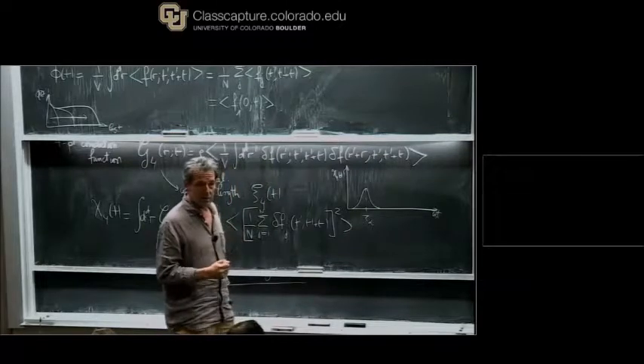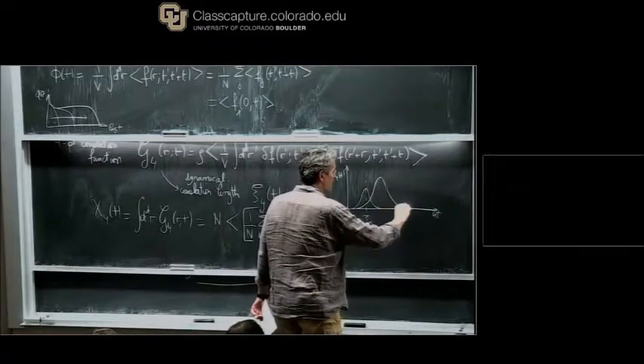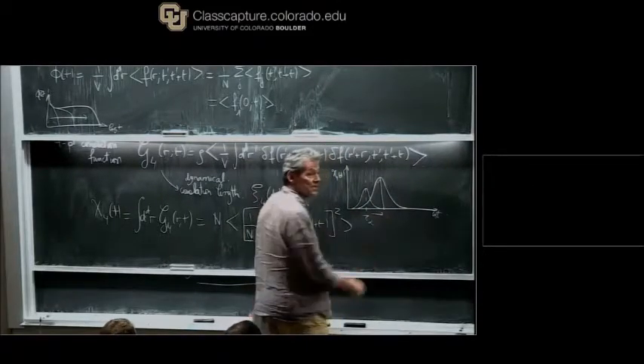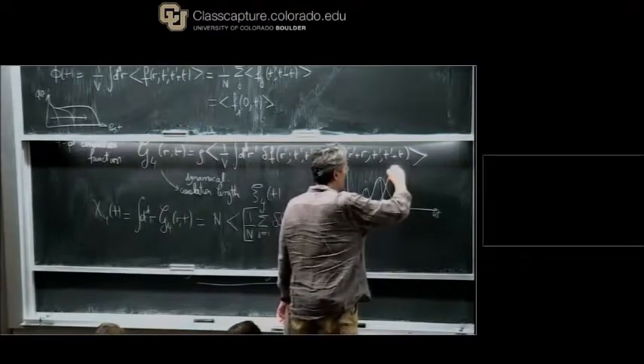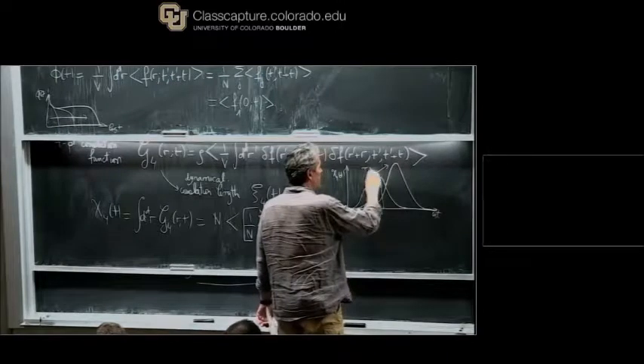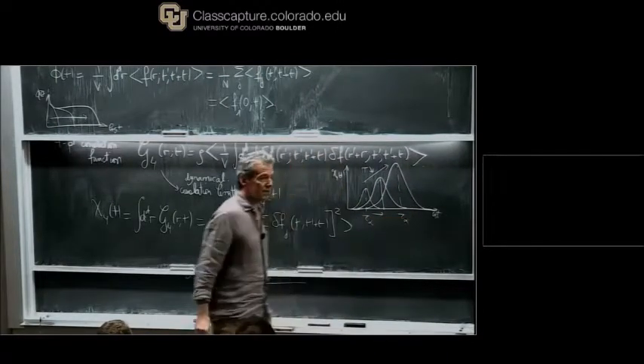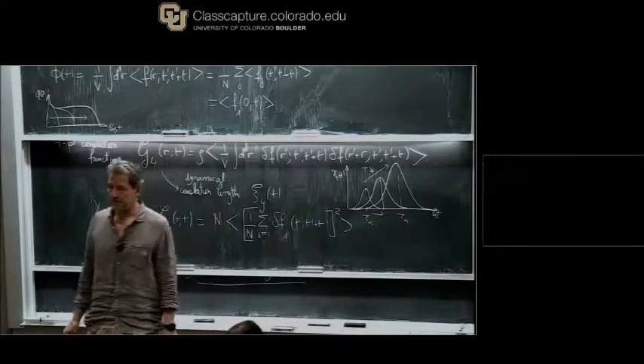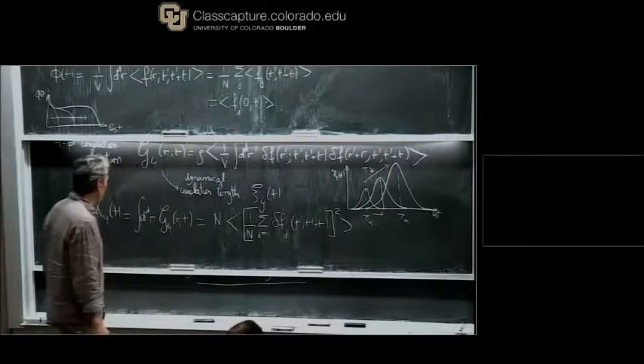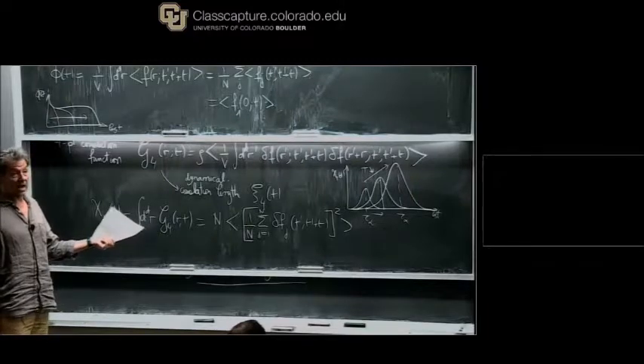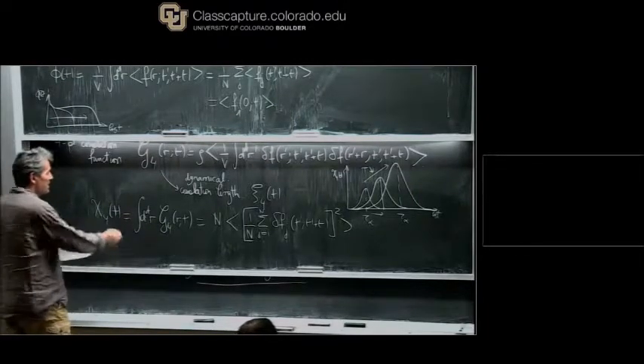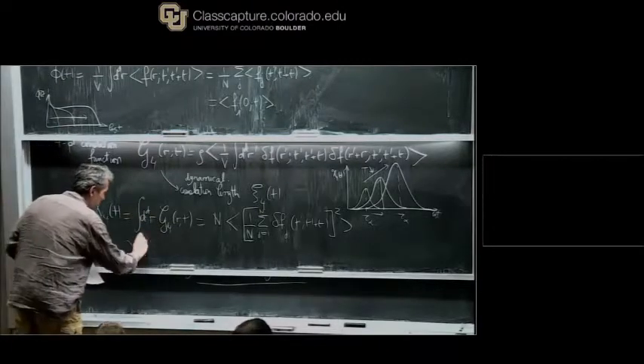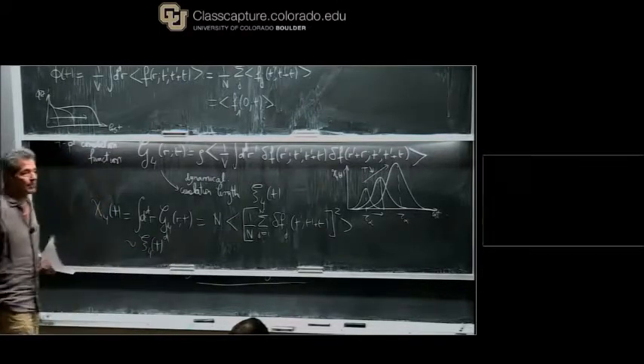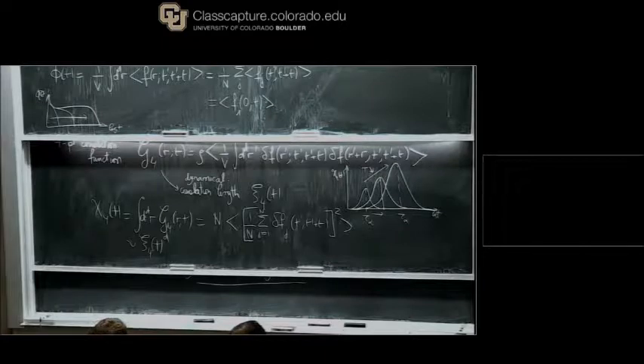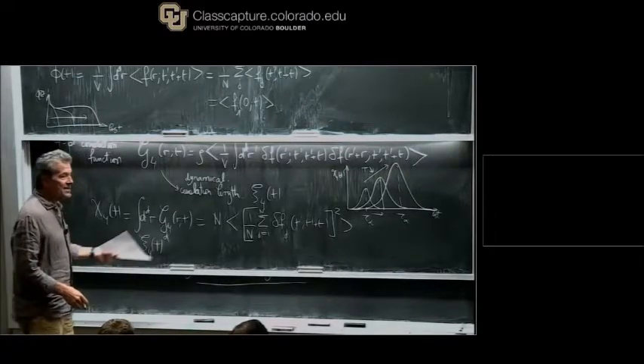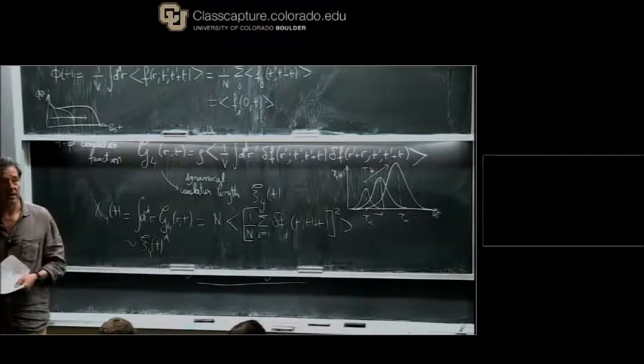Now, when you lower the temperature, that function increases more. Tau alpha, of course, is displaced, as we know, by 15 orders of magnitude, and you observe this kind of behavior. So as the temperature decreases, tau alpha shifts, and the maximum of the function increases. Of course, if you do some naive dimensional scaling analysis, you would say it goes like a volume, so this is roughly the correlation length to the power d. Well, it's too naive. It's not exactly true. The exponent is not very clear. But let's say it scales at least like some power of the correlation length.